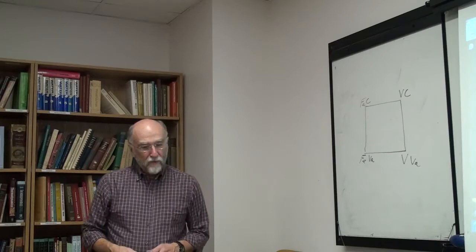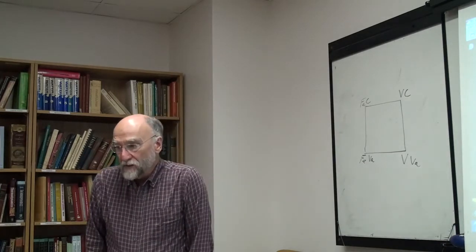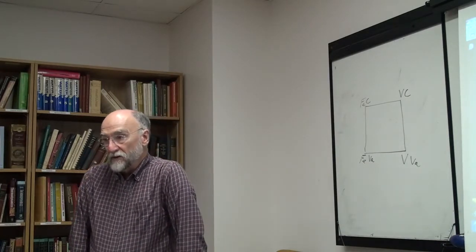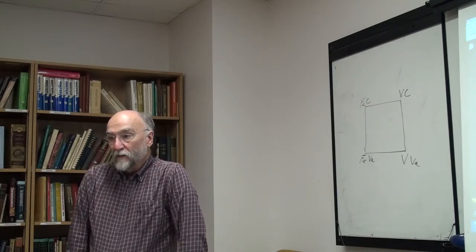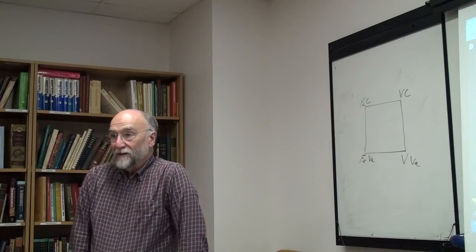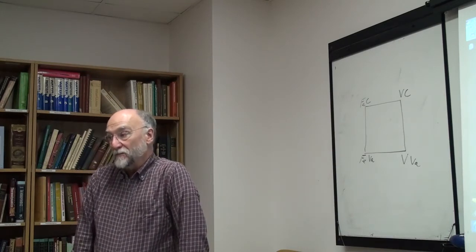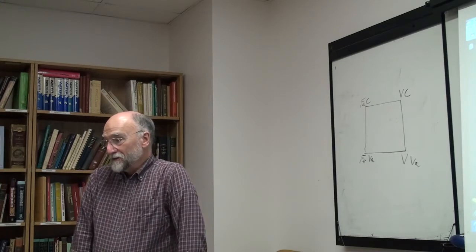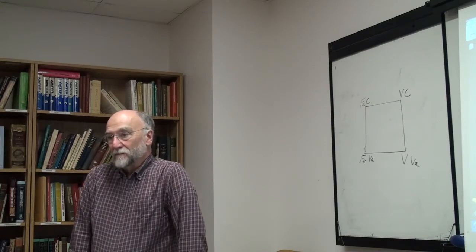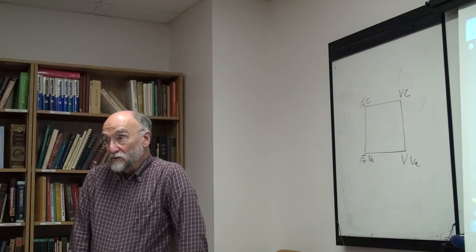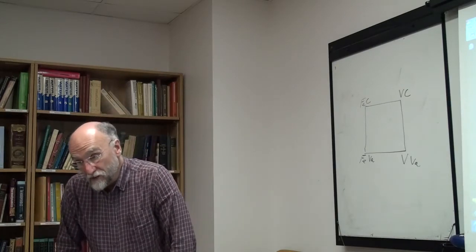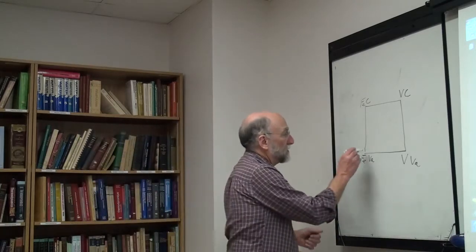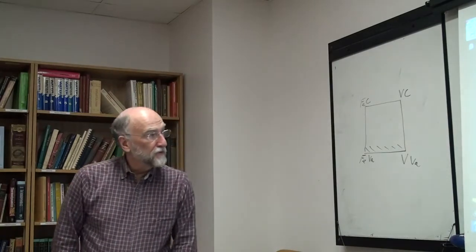We're talking about 2 sublattices. The 2 sublattices are the metal sublattice, onto which the iron and vanadium randomly mix, roughly, and the interstitial sublattice. In the pure metal, the interstitial sublattice is empty. It contains only vacant sites. And then your carbon goes into some of the vacant sites. So we're really only dealing with a system that's quite dilute in carbon, a few percent at the most.